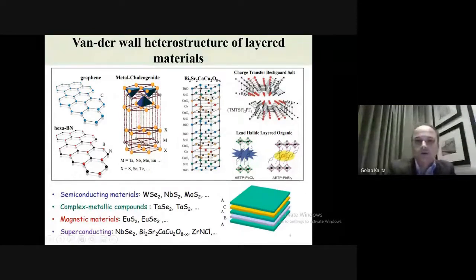Okay, so not only MoS2 and graphene, then came hexagonal boron nitride. Hexagonal boron nitride is the same as graphene. You can have almost the same lattice constant as graphene, with just around 2% mismatch. So what if you replace these carbon atoms by one boron and one nitrogen atom all over here, then you can have hexagonal boron nitride. But in hexagonal boron nitride, you don't have any free electron, or you don't have an sp2 pi electron. So it becomes an insulator with a band gap around 6 electron volt.